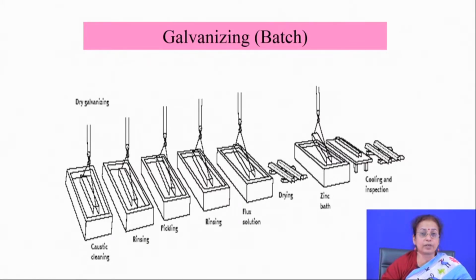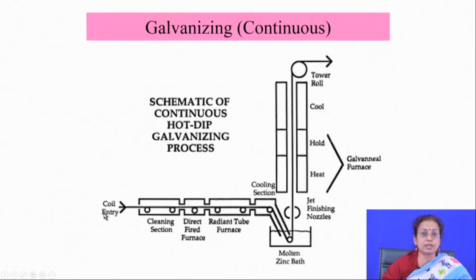Prior to hot dipping, you can go for flux solution dipping, so that your surface is no more oxidized prior to your zinc coating. Then go for drying, then zinc coating, and then cooling, inspection and dispatch of the component. These are the steps which are followed, and this is a kind of batch processing. You can also make it continuous processing with an arrangement where you have the cleaning section, direct fire section, hot dipping section and withdrawal section, kept one after another.